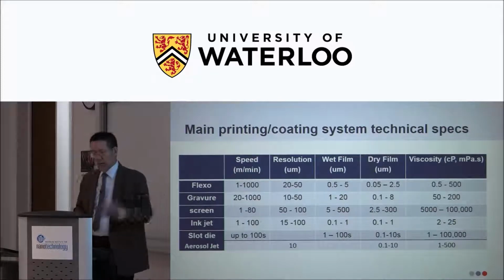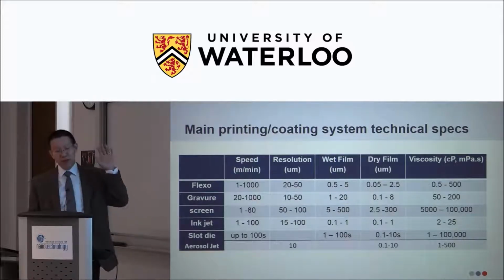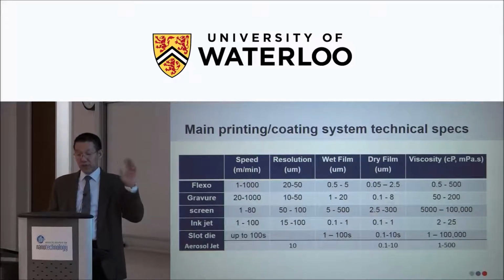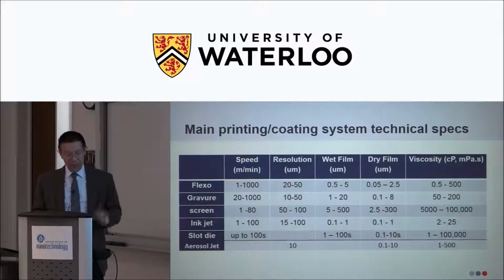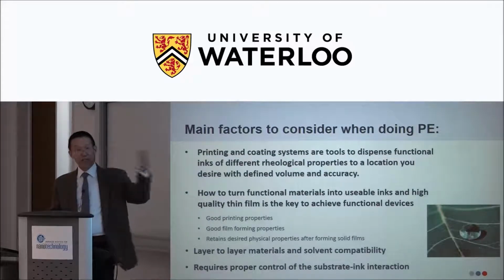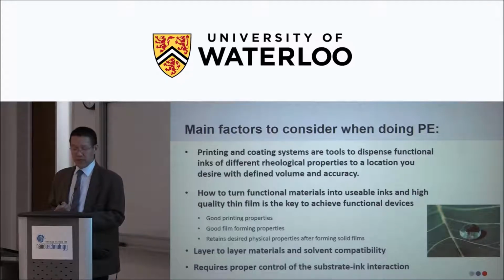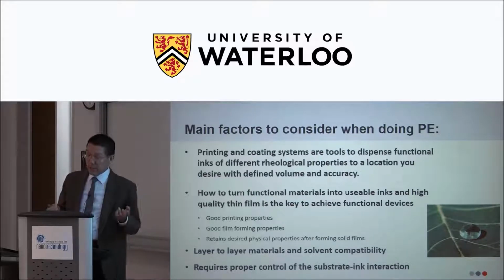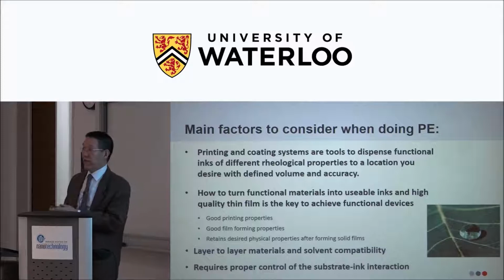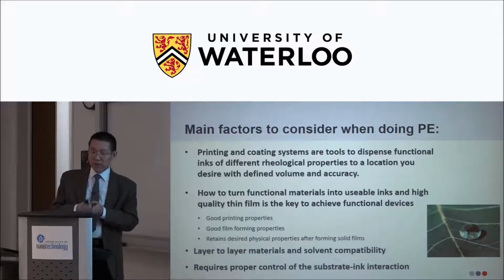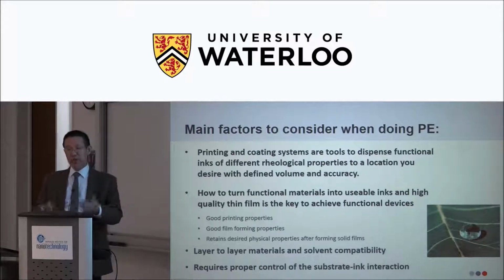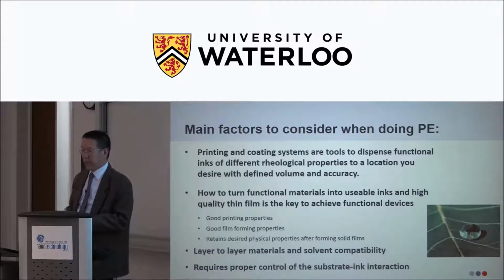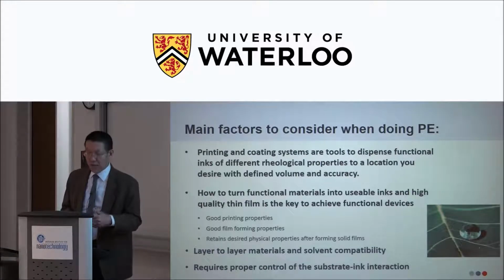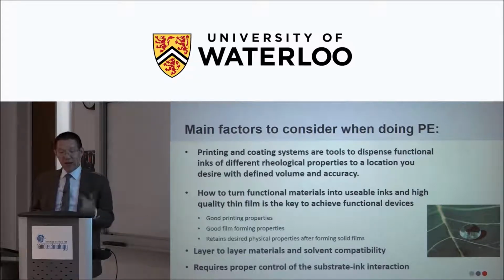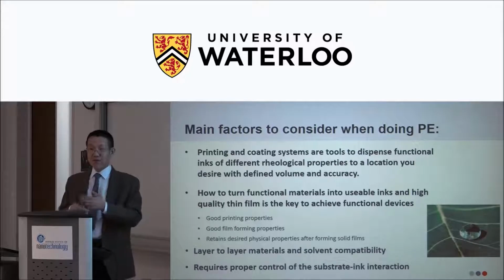So we have a series of printing systems that will give you different printing speed, resolution, and film thickness. But when you look at those systems, they have different names, different printing mechanisms. By the end, it is a system that allows you to dispense functional inks to the locations you want, right? With defined resolution, volume, and accuracy. But when you look down to the bottom, to make printable devices you need to find a way to turn functional materials into usable inks first, and how to print them, then how to achieve the functional film after they dry up.